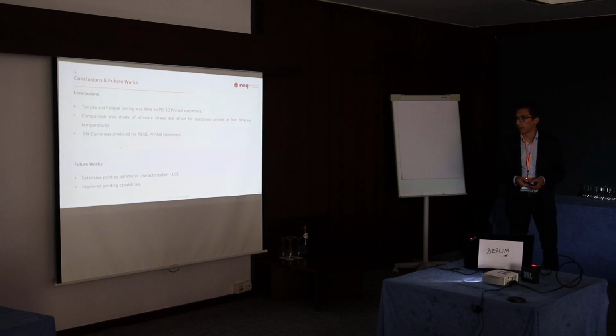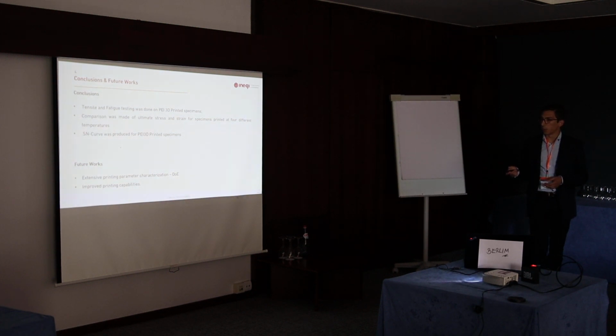In terms of future works, we believe that we need to be more extensive in the study of parameters that affect the mechanical behavior of our specimens, as clearly temperature is not the only factor, or even probably not the most important factor in this case. And we also found that we need to improve a bit our printing capabilities, because as you can see in the photos from the breaking surfaces, our geometry is not perfect, and this might also influence the results that we're having. So we really need to improve on this.